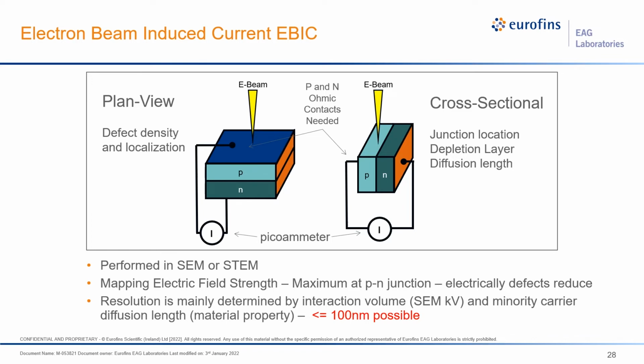Ultimately, the resolution is going to be mainly determined by the interaction volume that I showed before, which is then related to the accelerating voltage in the SEM. And it's also a bit related to the minority carrier diffusion length of the material itself. So materials like gallium arsenide will have slightly different ultimate resolutions than, say, gallium nitride.